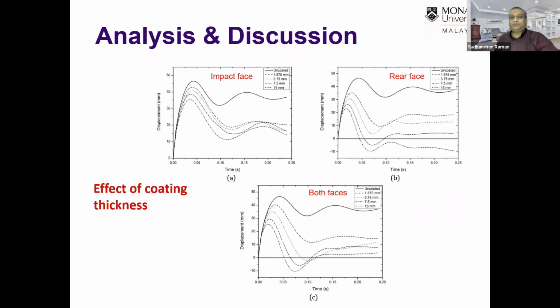For example, what we have done is we have applied the coating on the impact face, on the rear face, as well as both faces by using different coating thicknesses. The uncoated here refers to the control specimen, which was just a bare panel. 1.875 constitutes 2.5% coating on the impact face, up to 15 millimeters, which is 20% of the panel